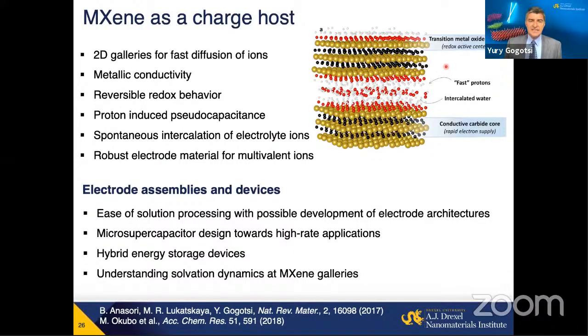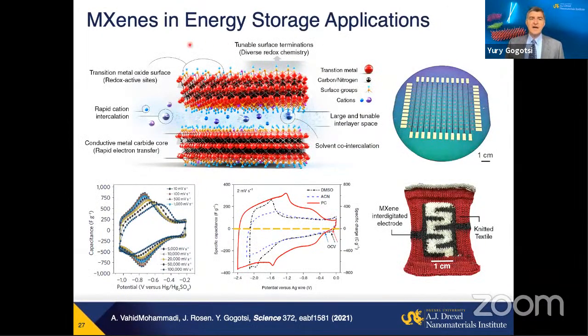They have metallic conductivity, which is an order of magnitude higher than reduced graphene oxide. They have transition metal on the surface that can change its oxidation state. And they have channels between the layers where ions can move in aqueous or non-aqueous electrolytes. So that's potentially why MXenes are so attractive for energy storage applications, whether we're talking about larger scale devices, but first of all for micro scale, printable on-chip or wearable devices.